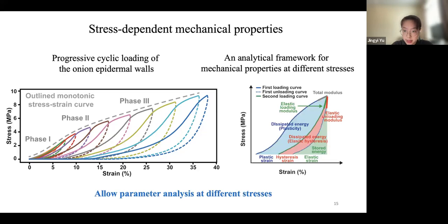So from the monotonic loading, we already showed that the overall stress-strain curve is nonlinear, and from the cyclic loading test, we see that by stretching the wall cyclically, we can analyze different kinds of mechanical properties. So in order to study how these different wall mechanics evolve and change at different stress-strain levels, we stretch the wall progressively and cyclically to different strain levels across different phases of the cell wall. And we developed this analytical framework that is able to decompose each cyclic loading test by different aspects of mechanical properties, allowing us to quantitatively analyze different wall mechanics at different stress and strain levels.